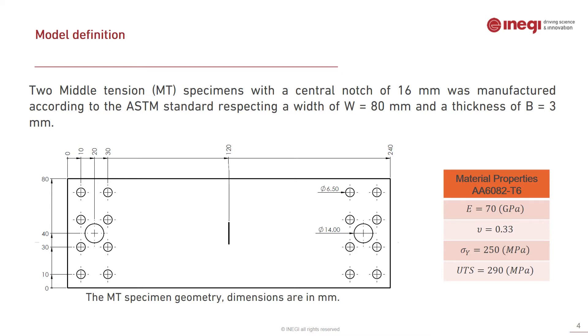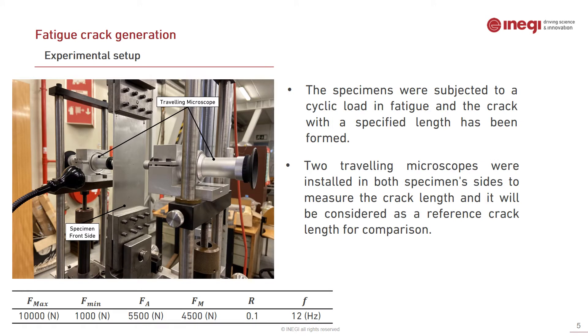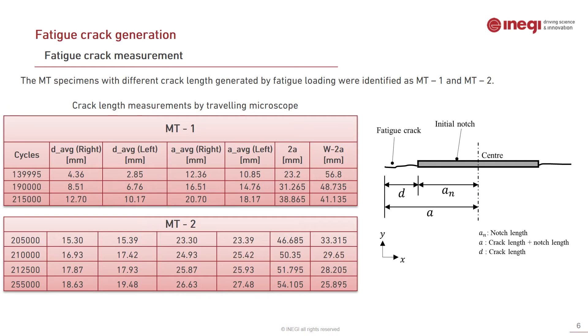The material properties used for the study and the experimental setup for fatigue crack generation are shown here. The specimen is mounted in a 10 kN tensile machine, and two travelling microscopes were installed on the front and rear sides to measure crack length. The maximum load was 10 kN with a load ratio of 0.1. The specimens were identified as MT1 and MT2 (Middle Tension 1 and 2). The fatigue crack is defined as 'd', and the fatigue crack with the initial notch 'a_n' reaches total crack length 'a'. Two tables present the corresponding crack length measurements versus cycles.